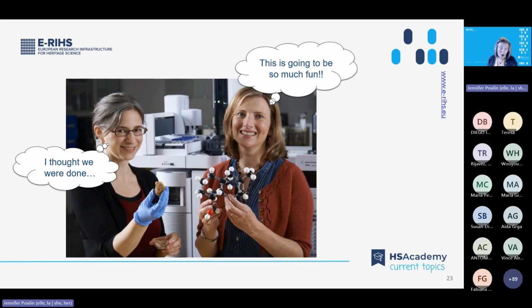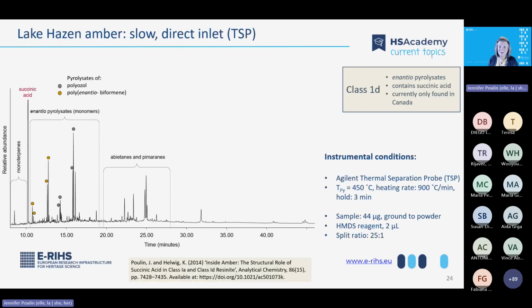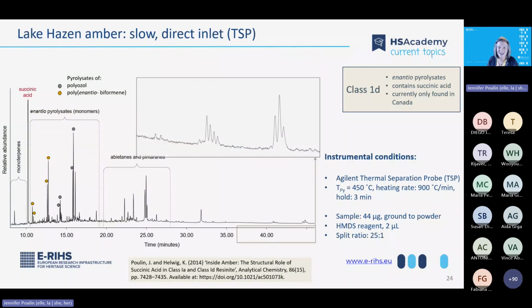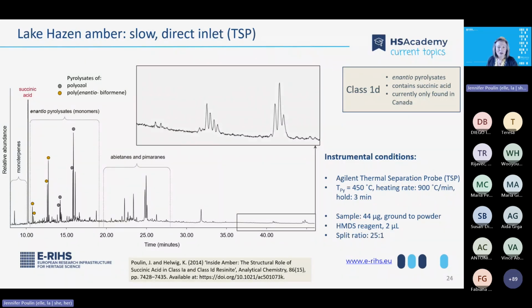And I decided to run all the amber references again at 450 degrees Celsius using slow pyrolysis. And here's the same class 1D amber sample run using slow pyrolysis with the TSP at 450. And we see some similar results. You see the significant peak of succinic acid, pairs of labdane pyrolysates, monoterpenes, pimaranes, and abietanes. However, there's something really exciting and different that's happening at the higher retention times. And before I show you, I want you to remember these 4 labdane alcohol pyrolysates right here, because they're important.